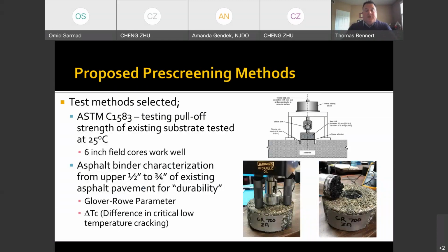And so what we did is we looked at a couple different tests. This one is fairly simple to use. This is ASTM C1583. It can be done on a 6-inch diameter core. We make a little bit of a core cut, a pre-core cut into the HFST. You can see in the picture below, through into the asphalt material, and you actually can pull it, and you can see the pull-off strength of the HFST.